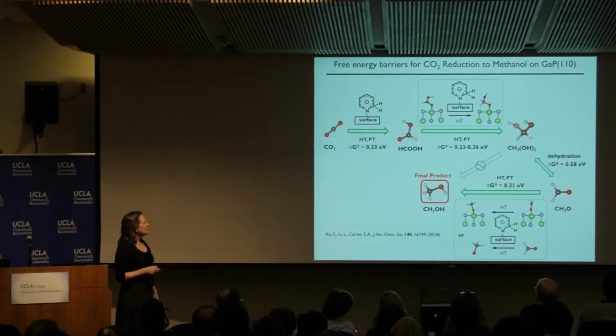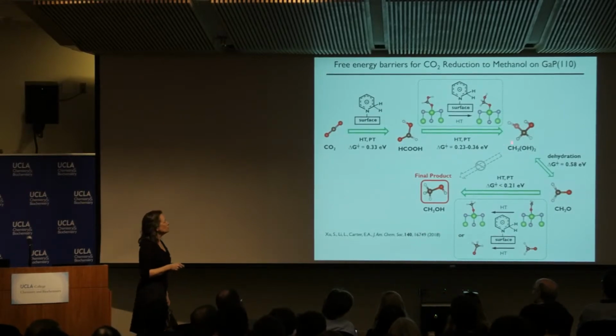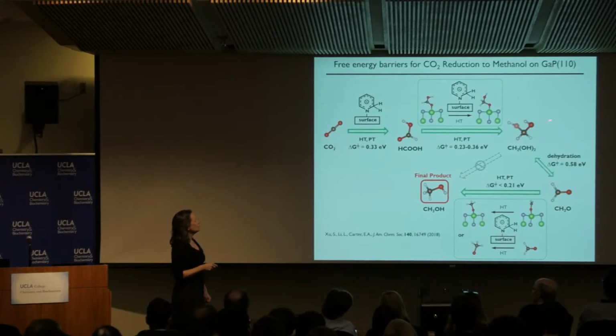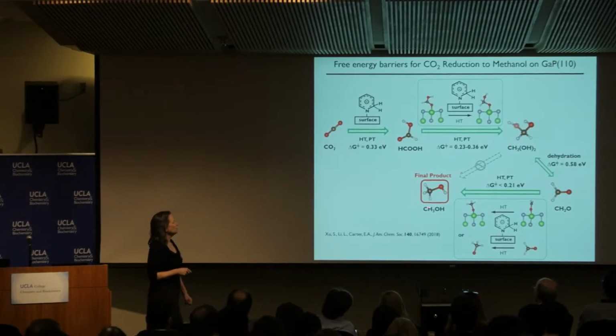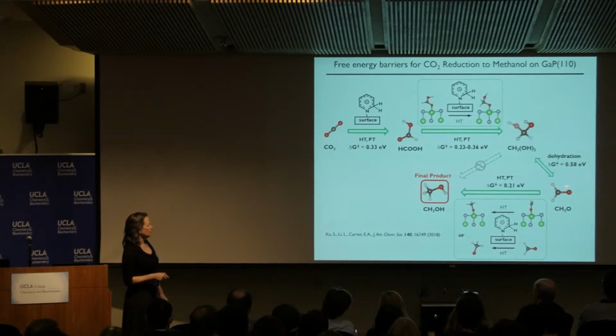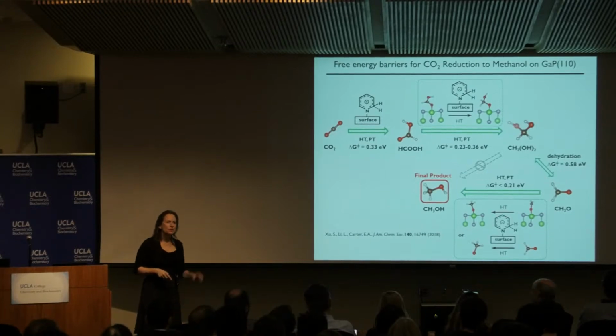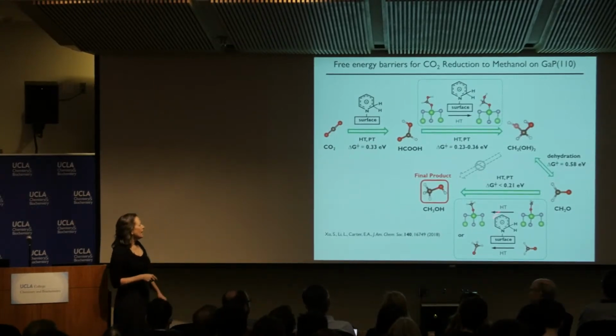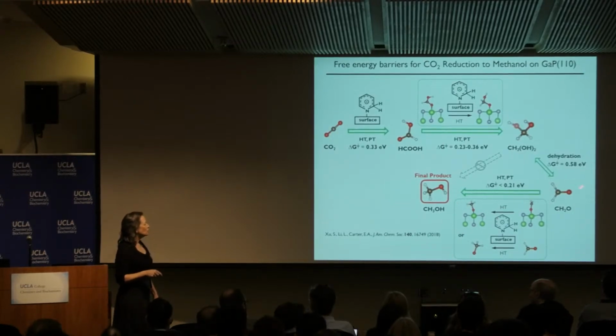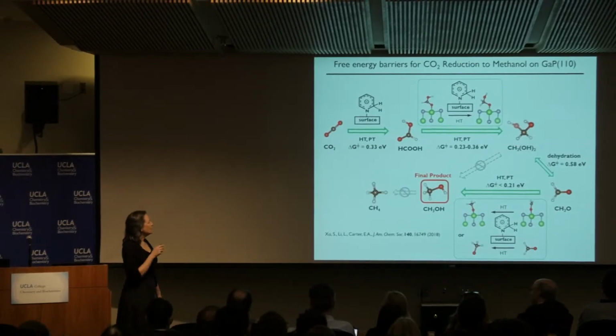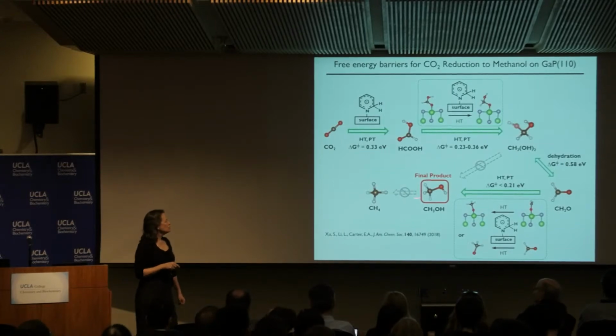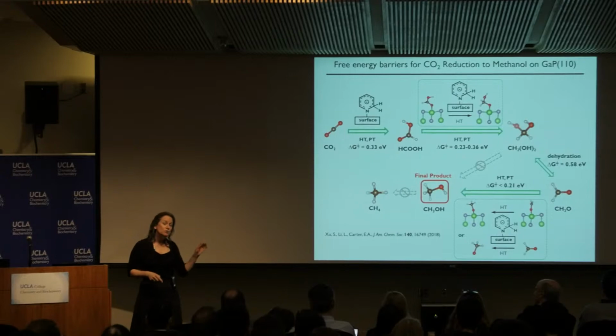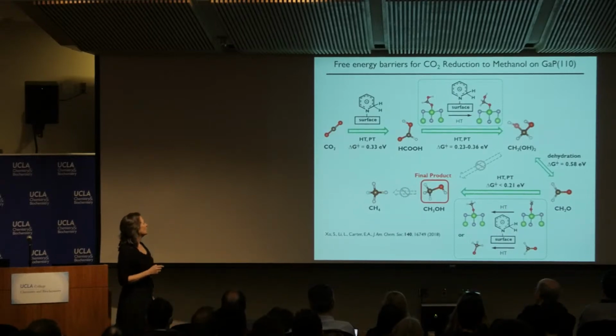So the interesting thing is then we showed that you can't go directly to here. This is the high barrier to go from the dihydroxymethane to methanol. But if you go through formaldehyde, either in solution or on the surface, you have a very low barrier. So having the 2-pyridinide on the surface and reacting with formaldehyde rather than the dihydroxymethane is the key to making methanol. And then he went on to show that there's a very high barrier to take methanol to methane. So that explains why you don't go to methane and why you end up with methanol.